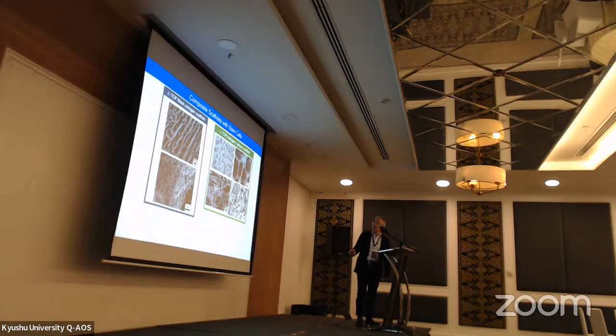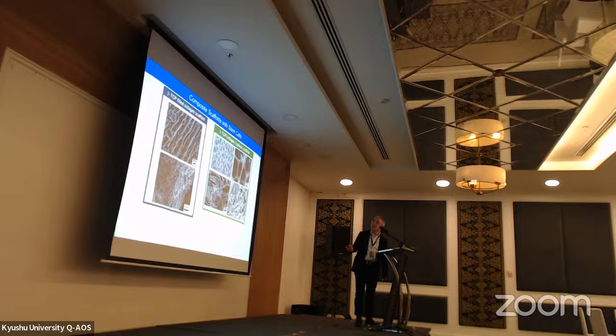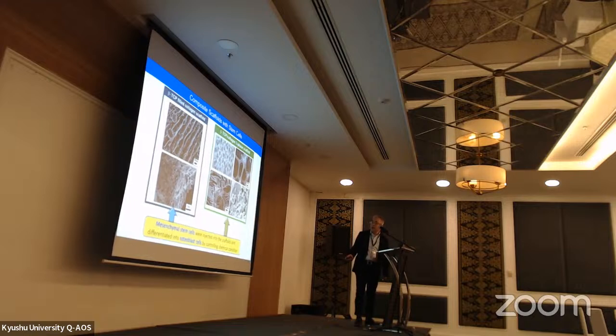Okay, this is another biomaterial we developed. This is beta TCP, a bioceramic very similar to hydroxyapatite. We prepared a collagen scaffold in which beta TCP particles are distributed, called beta TCP filled collagen scaffold. And also another type of scaffold: we first prepare a beta TCP porous structure, then introduce a spongy collagen phase into this porous structure. The basic materials are the same, beta TCP and collagen, but the structure is different. Then mesenchymal stem cells were injected into the scaffold and differentiated into osteoblast cells, which create bone tissues.